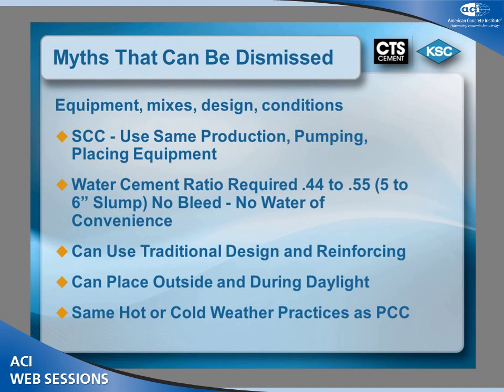Interestingly enough, we're using a higher water cement ratio. The shrinkage compensating cement requires that. And that water is used up, but we're actually able to deliver to a job site a good 5 or 6 inch slump concrete, not a 2 inch slump concrete, not a 1 inch slump concrete, which is very nice and very favorable by the workers themselves.